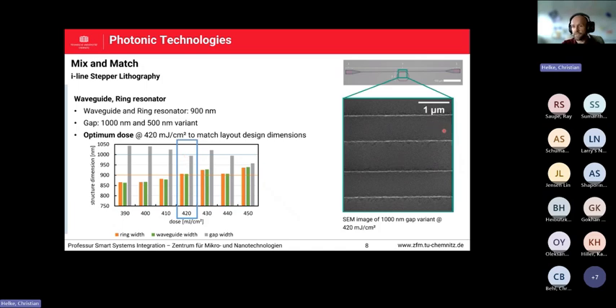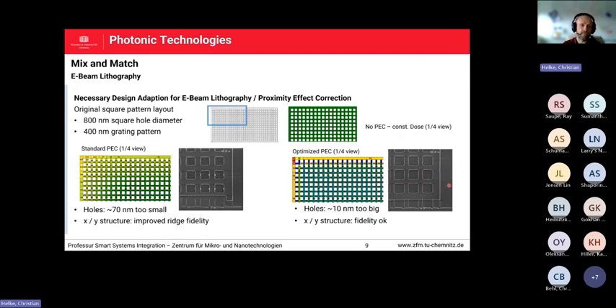So here are SEM images. The upper part here is the waveguide. It's 900 nanometer, and then you have the 1 micrometer gap to the ring resonator, which is showing here. And so we decided here to go for an optimum dose of 420 millijoule per square centimeter for our I-line stepper process. Then going to the E-beam part itself, which I mentioned, the in and out coupling structures were here the aim in this exposure so far.